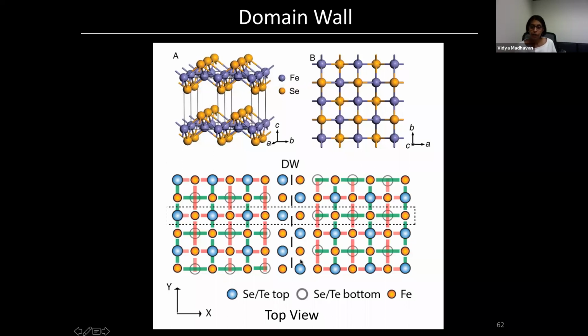Because the crystal structure allows you to do that, you naturally find such domain walls in your sample. And because there's this funny, strange phase relationship between the top and the bottom, across this particular kind of domain wall, we expect the superconducting order parameter to have a pi phase shift. So it's a serendipitous discovery. It's not something we engineered.